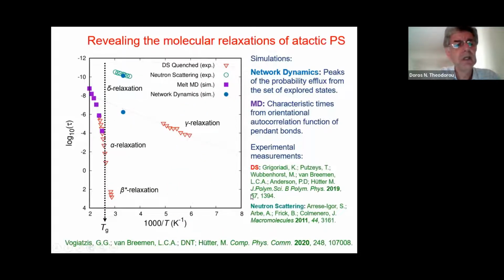Here I show these time constants as obtained from the landscape picture, the 10 to the minus 6 and the 10 to the minus 10 seconds at room temperature, in a log relaxation time as a function of inverse temperature plot. And it seems that these characteristic times that are obtained from the landscape simulation are representative of what is called gamma and delta relaxation in polystyrene, as measured experimentally by dielectric spectroscopy and neutron scattering measurements, which are shown by these red triangles and these petrol-colored rings, respectively.